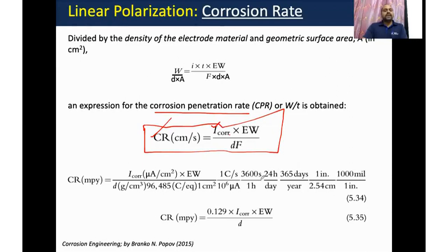So now the question is how to measure the polarization resistance. There are basically 3 techniques to measure the polarization resistance. The system will be polarized, but how are we going to measure it? There are 3 different ways we are going to discuss here. First is the linear polarization technique. It means we apply continuous current and measure the change in the potential, to estimate the instantaneous corrosion rate under various process conditions.